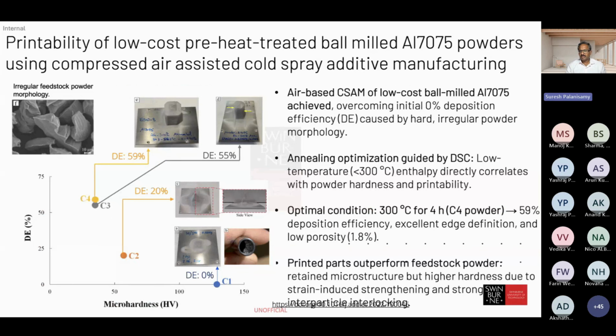Another very important thing is, we talked about the different process parameters and different conditions that impact. Again, the powder particle raw materials I spoke about earlier. This powder was a low-cost powder achieved by ball milling. When you think about 3D printing applications, you'll always talk about spherical powder particles. But cold spray doesn't need spherical powder particles. Different shapes are also fine because you're more looking at the flowability of the powder. However, sometimes in the nozzle, what you're looking at here, it can get clogged. So you have to be very careful when you do the printing.